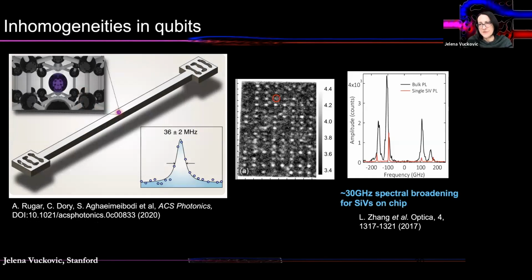But then going back to the question of material science, we and others have to spend a lot of time, and are still spending a lot of time, addressing material science issues such as inhomogeneities in qubits. And of course, for any scaling of quantum systems, these inhomogeneities are a very big problem, because if you have discrepancy between their transitions, it is very hard to build systems consisting of hundreds, or who knows, eventually maybe millions of qubits. And that inhomogeneity could also be seen in our measurements. These are spectral measurements for silicon vacancies, which are showing inhomogeneous broadening of about 30 gigahertz, much smaller than for indium arsenide, gallium arsenide quantum dots that we used to work with, but still pretty important and significant, something that we need to work on.